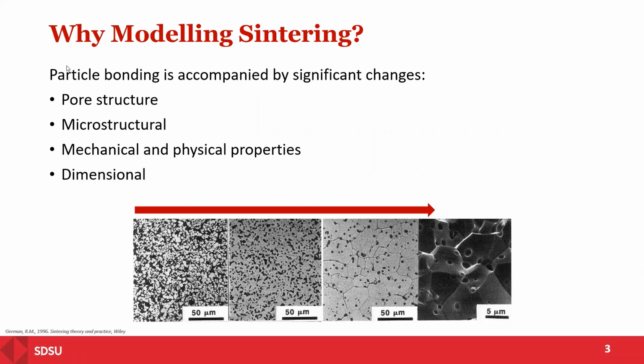Typically you are around 50% of the melting temperature. So in this process, you don't want to melt, unless in specific cases that we'll talk about, but you want just to have a promotion of diffusion phenomena. And that temperature, 50-60%, is the temperature where you actually activate and accelerate these phenomena. Because if you reach the melting temperature, you lose the geometry that you produce, and you don't want that.